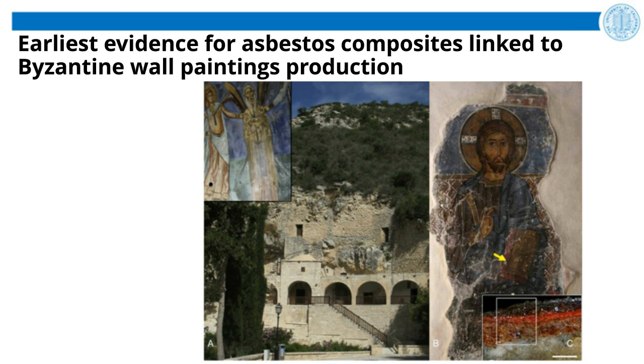From the top surface, we can see the dark brownish layer, most likely an alteration of cinnabar, which is mercury sulfide. Next, the intense red layer, most likely cinnabar, with some presence of hematite, probably, and an orange light brown layer, mostly hematite. And at the very bottom, we can see the plaster layer. The white square on image C shows the position of the sample area which was imaged in the SEM, shown on the next slide.